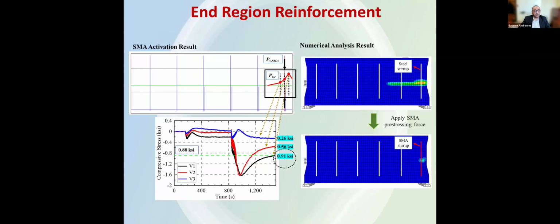And we found that we are able to apply a transverse pre-stress that reaches about 0.9 or so KSI, which our analysis showed that with this amount, we're able to almost eliminate all transverse cracks or splitting cracks that we see right there. We are actually going to be presenting on this topic next month at the ASCE Structures Congress, and we're now pursuing more testing to validate this concept.